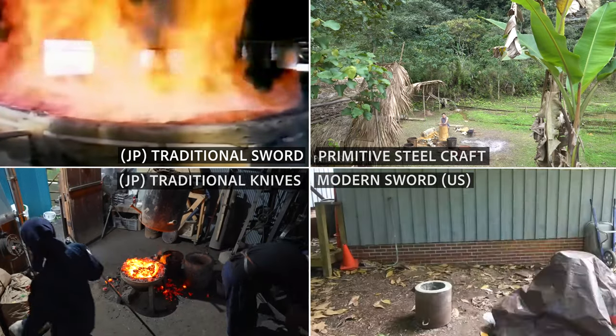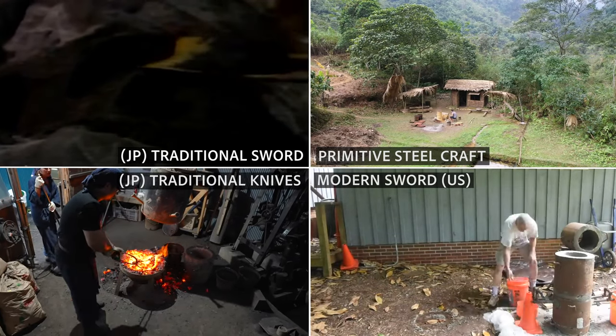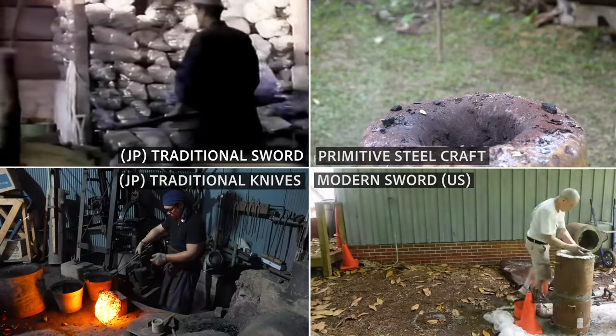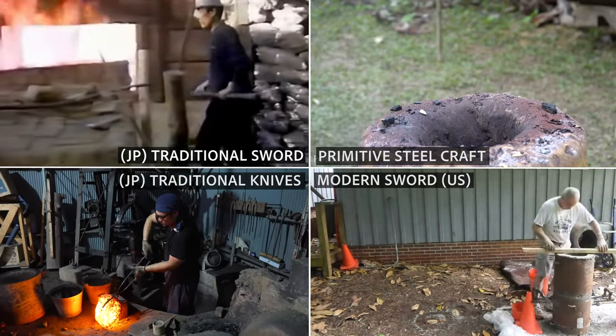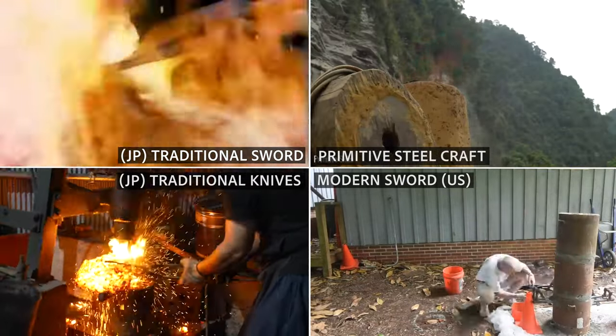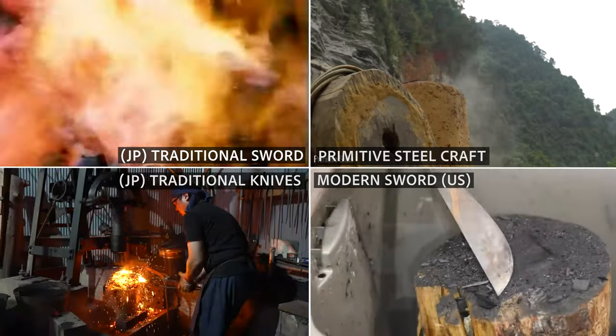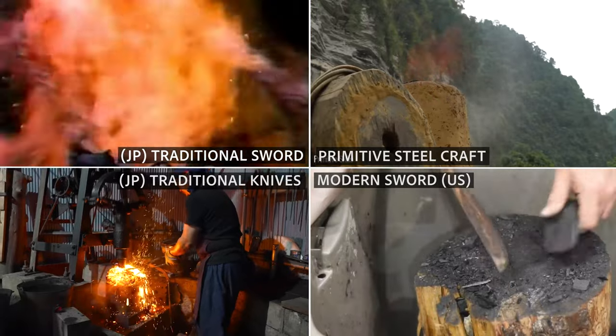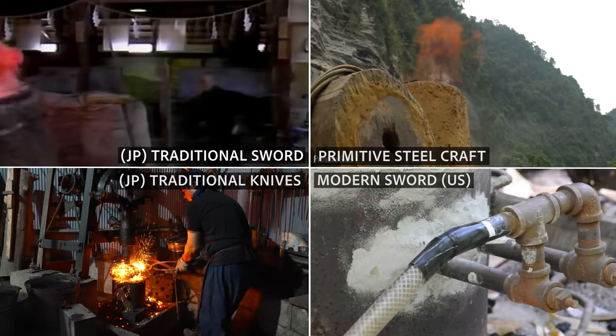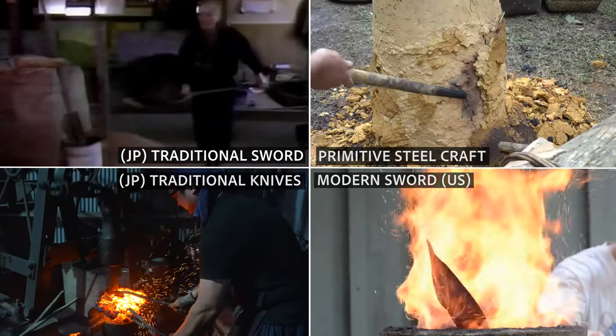The Kera is a lump, an iron sponge, a massive conglomerate of iron, steel, and slag. To sort out which pieces of Kera were Tamahagane and which were not, they broke the block into several pieces and performed several tests to classify them. If the small block analyzed was harder, breaks instead of bending, and was generally located in the outer zone of the Kera — hence why it was limited compared to the amount of Bukera — it was Tamahagane.